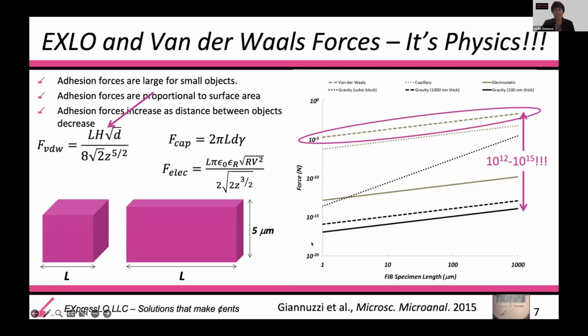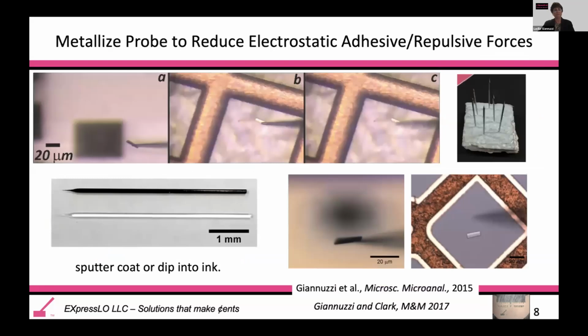Oops, sorry, there's an automated timer on that slide. The only material constant in this equation is the so-called Hamaker constant, and this varies only 2 orders of magnitude over the entire periodic table. So if you even subtract 2 orders of magnitude off of this van der Waals force equation, you still have an extremely large contribution of the van der Waals forces with these sizes, with respect to these surface areas. And so this is why this technique works, and why it works extremely well.